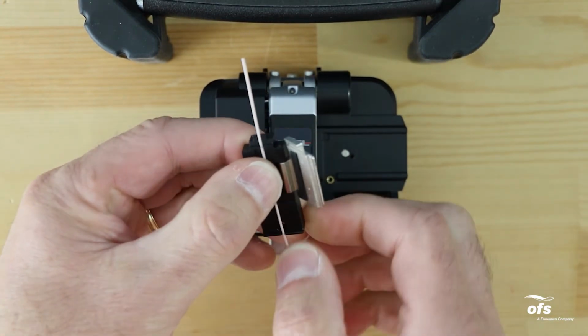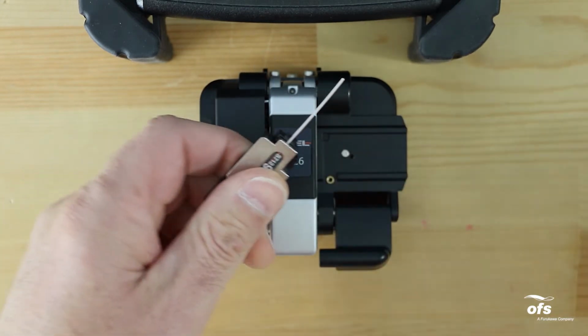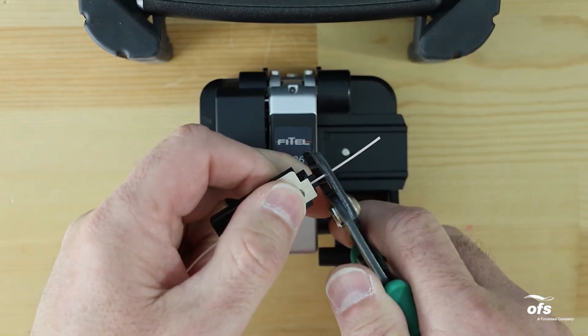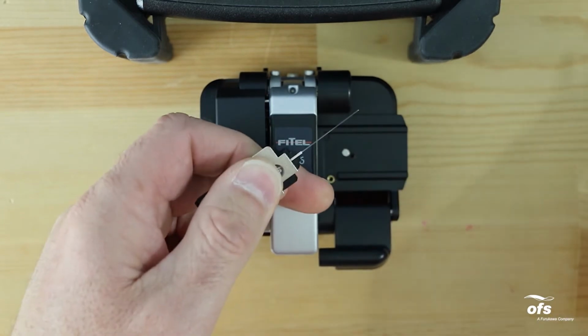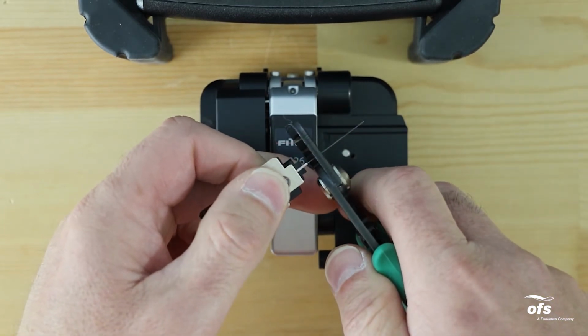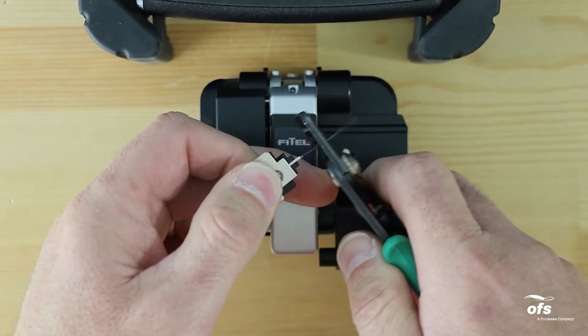You can also put fiber into the holder, leaving approximately 30 millimeters of 900 micron and 250 micron coating from the end of the removable holder, and strip the 900 micron and 250 micron coating from the fiber, leaving bare glass. Strip as close to the end of the holder as possible.